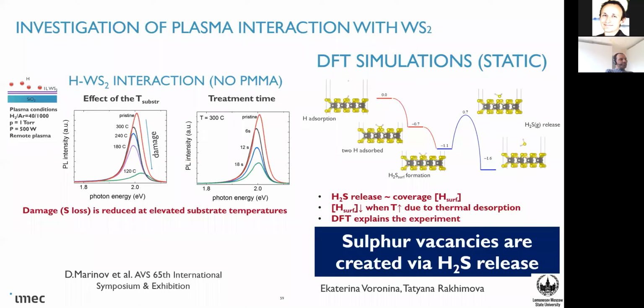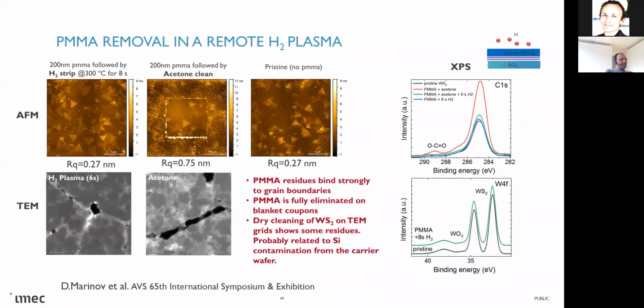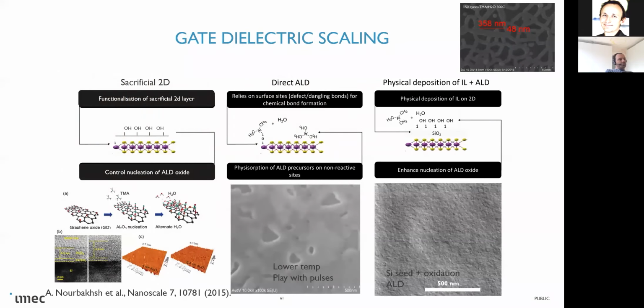We understand pretty well the mechanism of how it's working. We did some DFT calculations, and basically it's really the amount of hydrogen. You need to reduce as much as possible the amount of hydrogen at the surface, because if you have too much hydrogen at the surface, it's inducing sulfur vacancies. Therefore, it's even working slightly better at higher temperature compared to lower temperature, because you have less hydrogen adhesion at the interface. It's pretty efficient, but we still suffer from some etching effects at grain boundaries. We are still refining this method, and we think that we have something there.